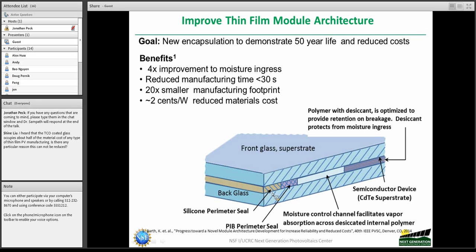The second step is to have a polyisobutylene material which is very low in moisture ingress, so that a very small amount of moisture gets in.